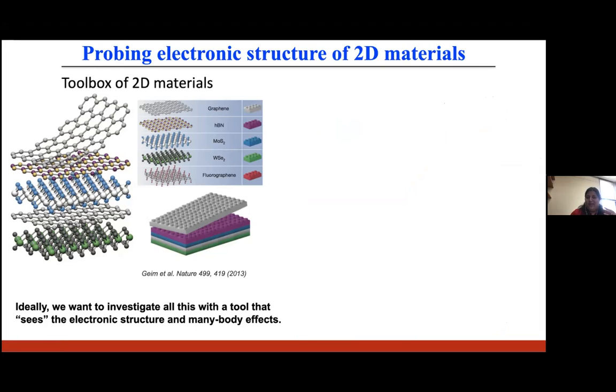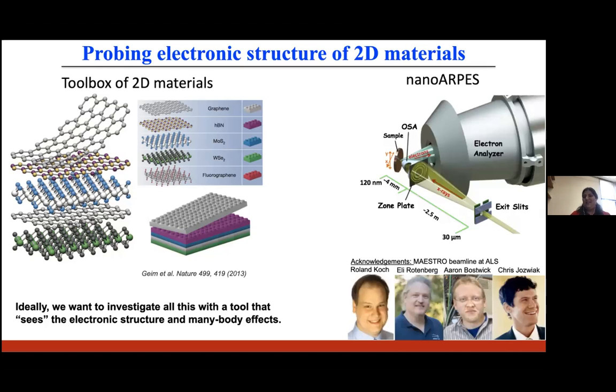Okay. And this is great, but if you think about it, traditionally ARPES has a very large beam spot size, which means that you can only investigate the electronic band structure of millimeter size samples. But typical 2D materials or heterostructures have a mesoscopic size. So it means that if we want to probe their electronic band dispersion, then we need a next generation ARPES frontier, or focused ARPES, focused or nano ARPES. And so my group primarily uses the nano ARPES end station at the MAESTRO beamline at the Advanced Light Source, where with the zone plate, you can actually achieve a spatial resolution reaching up to 120 nanometers.